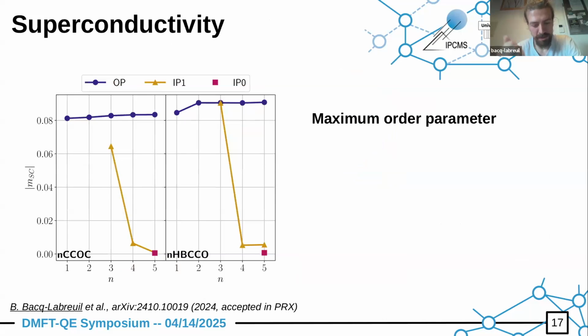So this inhomogeneous doping has some very important consequences on the superconducting properties. And that's where we believe we can start to understand this dome shape of the critical temperature that I showed a few slides before. What I show here is the maximum order parameter. We do the calculations for several levels of total doping, and then we look at the maximum order parameter for all these dopings. And we can separate the order parameter in the different layers.